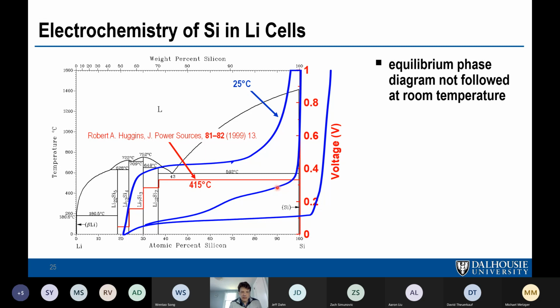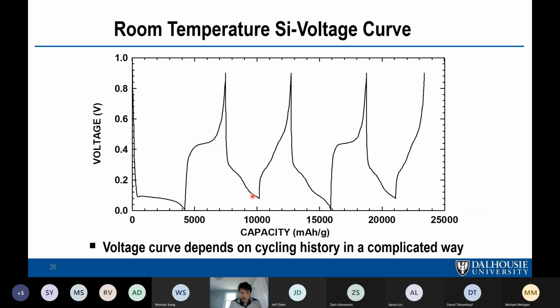But when you lithiate again, now you have a sloping voltage curve, indicating two single-phase regions. So not only is the equilibrium phase diagram not followed, but the voltage curve is dependent on history. And that could be shown even better here. If you lithiate silicon, you have a two-phase region, delithiate, two-phase region, lithiate again, you have single-phase regions. And if you don't go all the way down to 0 volts, single-phase regions again, but then you go to 0 volts and that two-phase region reappears.